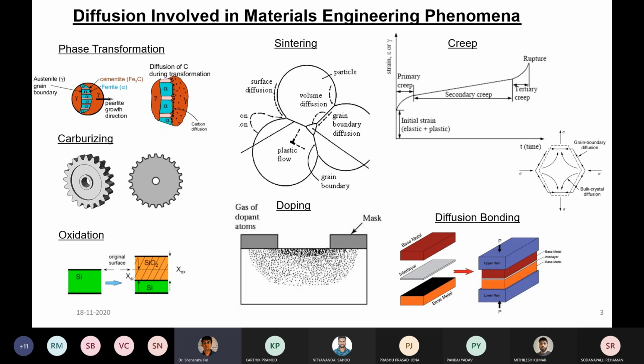So how is doping happening? If you check the picture, on the surface at a certain temperature, slowly the dopant atoms go inside the substrate. This is also indicating that diffusion is very important with respect to the doping process. If you want to design MEMS, lithography, etching, in all these areas of doping, diffusion is a very important phenomenon. So understanding the diffusion process is very important. And there are lots of things, substitutional diffusion, interstitial diffusion, all those atomic scale mechanisms we will understand as we progress in this subject.